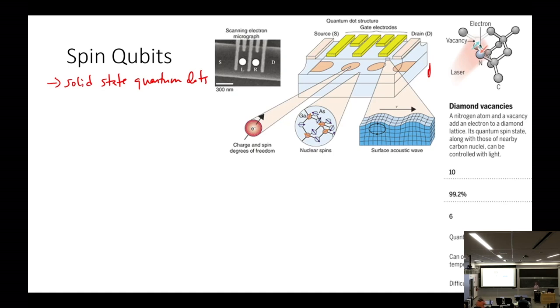And the most common way that they're made is by the so-called Stranski-Krastanov mode of thin film growth, where adsorbate islands form beyond some critical film thickness depending on strain of the growing layers. You typically start with a substrate and start growing film, and above a critical threshold, little islands that are nanoscale in dimensions buckle up out of the film, and that's the general way people make these kinds of epitaxial quantum dots.